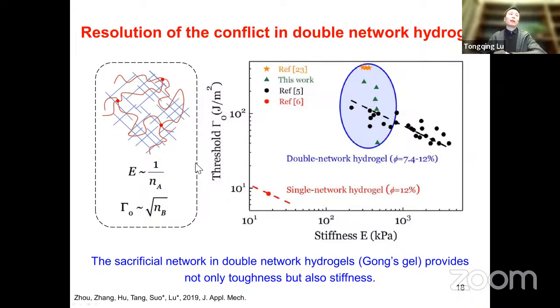And we found that actually in the design of these double network hydrogels, this conflict has already been resolved, because in these double network hydrogels, the modulus is determined by the short chain network, because the short chain network is very stiff, okay? But the fatigue threshold is determined by the long chain network. So these two material properties actually are decoupled in the double network hydrogels. So this conflict does not exist in double network hydrogels. So we see the sacrificial bonds provide not only toughness, but also stiffness.